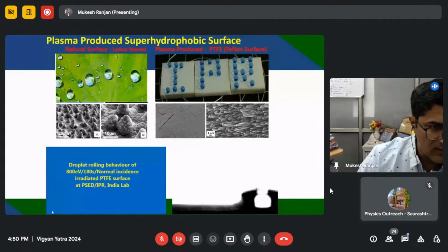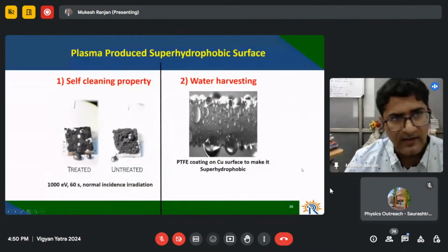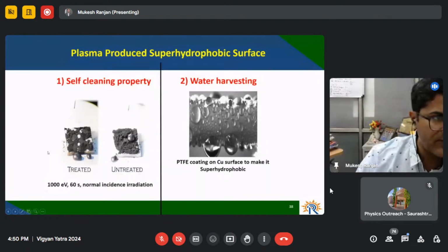So just to show you one movie. What you can see is that this surface is so nicely hydrophobic in nature that even when the droplet is falling, it is rolling very fast. And when we try to touch the surface, the droplet actually starts bouncing. It's not going. So simply by making nanostructures on the surface, you can make your surface super hydrophobic. It has many applications. The first example is self-cleaning.